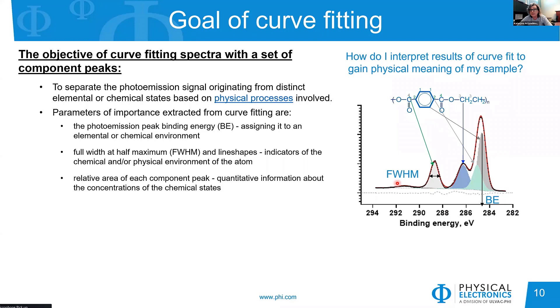Here's an example of a PET carbon 1s spectrum. When you obtain the spectra, you see multiple peaks that come from different types of chemical moieties present in PET, because they change the binding energy of carbon associated with those moieties. We interpret this based on parameters we can extract from curve fitting. The first parameter is binding energy — we look at the binding energy of all peaks and, based on reference data, identify what possible moieties can appear at that binding energy.